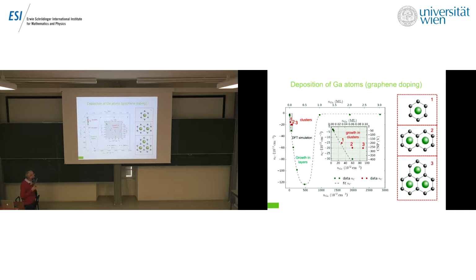And how to explain it? Simply, we found that with the growing number of atoms, the distance between the gallium layer and the surface was growing. So most likely due to that, the effectiveness of the transfer of electrons was getting smaller. But despite the decrease we see here, reality was different, and we had it at 0.2 monolayers, not 0.5 monolayers.